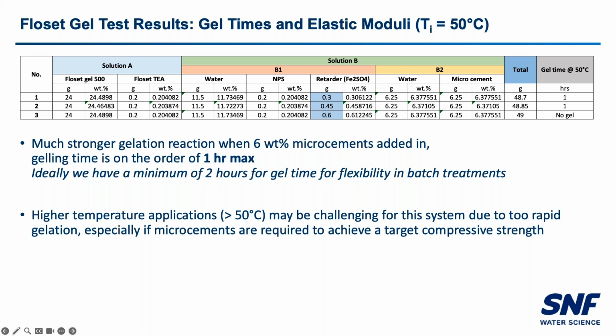So again, we can get rapid gel formation at 50 C, less than an hour. But again, if we push the system too much to try to delay it, or even using different delaying agents, we run the risk of pushing it into an area where we don't form gel at all. So the higher temperatures above 50 Celsius may be a temporary limitation of the system until we figure out ultimate compositions. These also have micro cements added, so again, we're looking for more rigidity, but those components will also accelerate the reaction. So not quite there yet with the higher temperature applications.